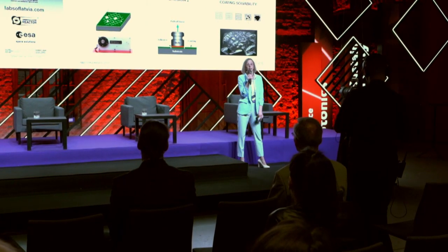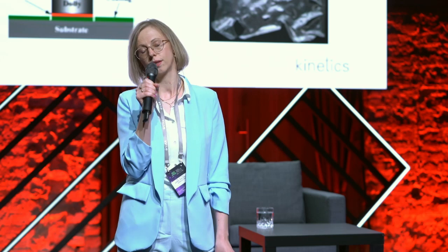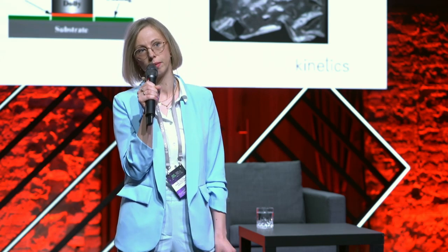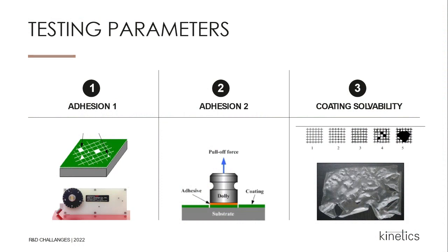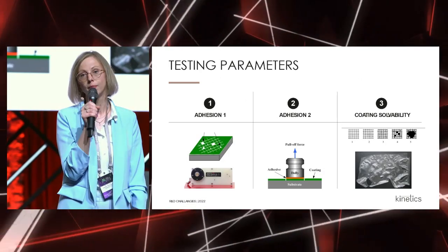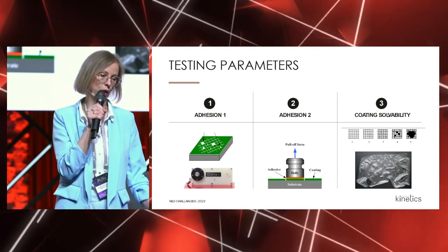And the final parameters are connected with adhesion, because for all coatings, this is one of the most important parameters, adhesion. And for us, it was very challenging in the beginning to find a substrate which we can use to compare compositions with each other. There were really many curiosities, because we tested animal bones, we tested beef horns, but unfortunately none of them was good enough due to their porosity. But now we have found 2 substrates which we use and can compare the coating adhesion with each other.